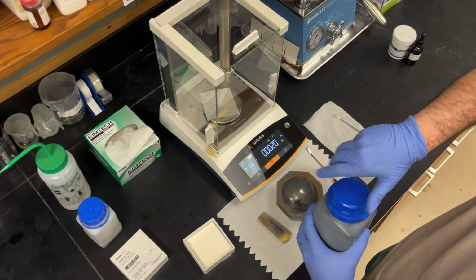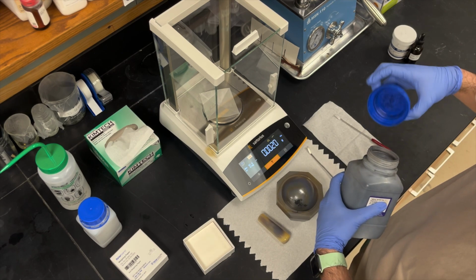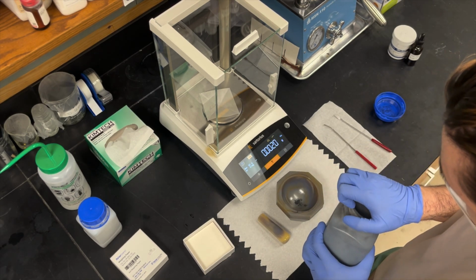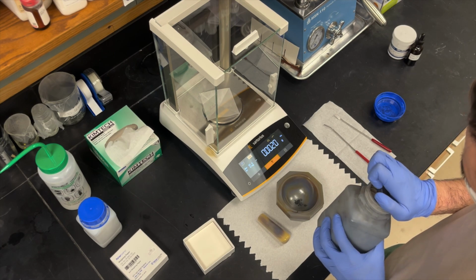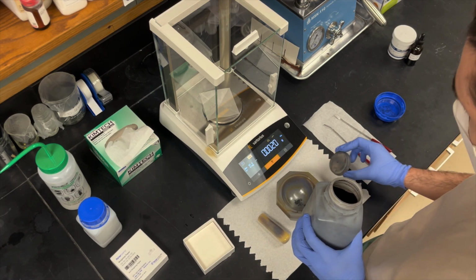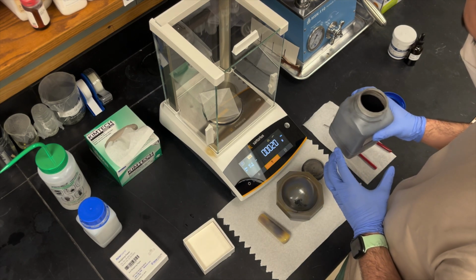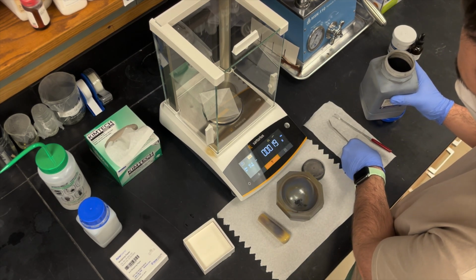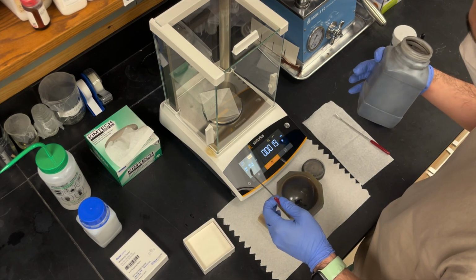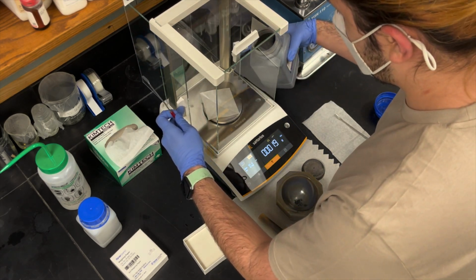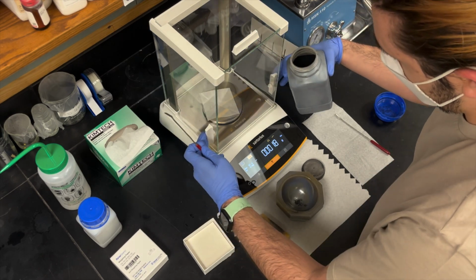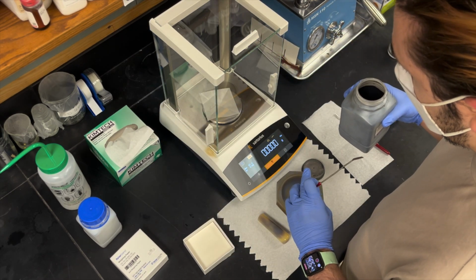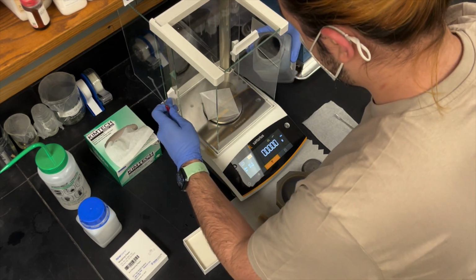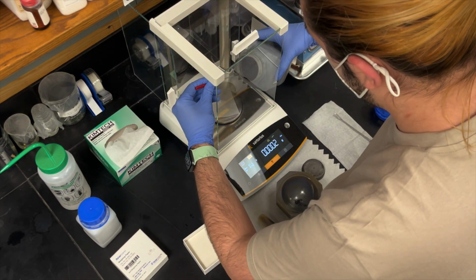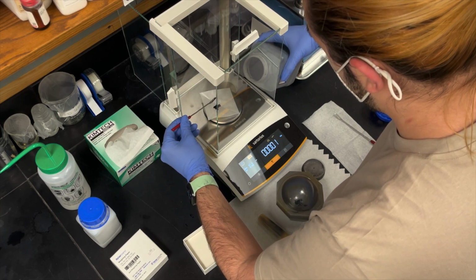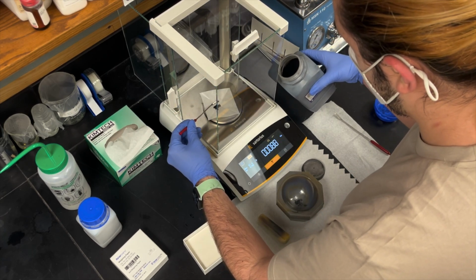Moving on to weighing out the carbon black, I'd like to note that another reason why you want to put in only a little bit at a time is because the densities of the powders do vary. So what appears to be 80 milligrams of the powder for the nickel, cobalt, manganese might be, let's say, 10 milligrams for the PVDF, or for the carbon black. So for this reason, you just want to be careful about how much powder you're adding in at a time, and try and start with a little bit until you get a feel for how much is an appropriate amount.